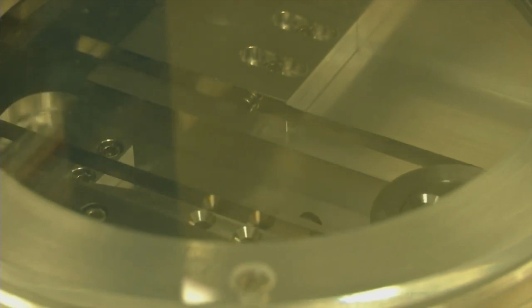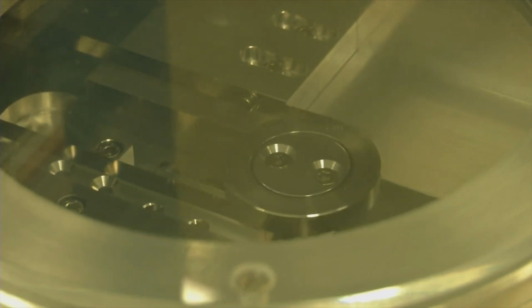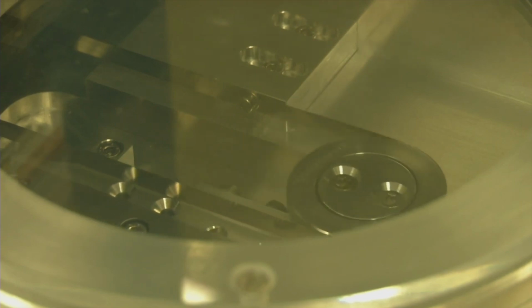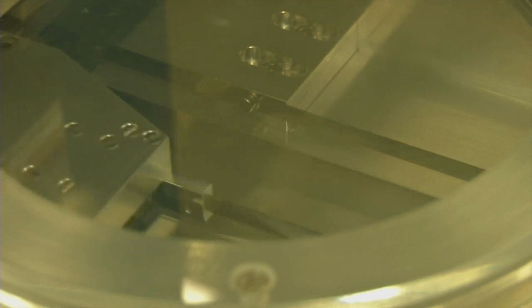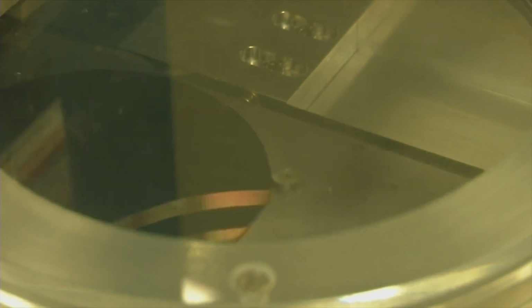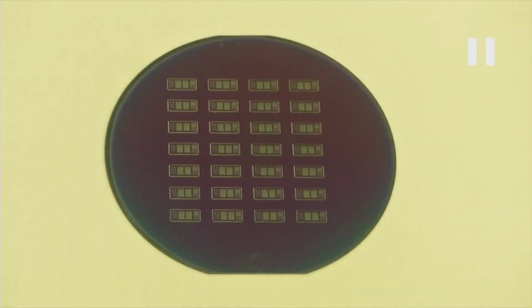So the robot arm goes in and it brings the wafer out. Now what we see here is an etched wafer. You can see these cantilevers are present here, and this is the silicon nitride part, right? The dark region that you see is silicon nitride, and this light region is silicon actually. So we removed this nitride and removed silicon as well in order to create an undercut, so that we create a freestanding cantilever.